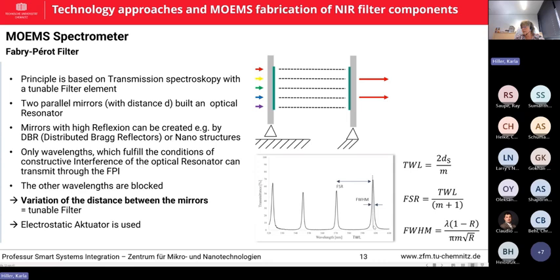And you can see here the transmission characteristics in a certain wavelength range. And this has some characteristic values like the maximum transmission. So 100% would be perfect. We end up maybe in the range of 60 to 70%. Then we want to have a narrow band filter. So this full width at half maximum should be as small as possible to have a good resolution. And we have also some limiting factors, for instance, this so-called free spectral range. So if the order goes higher, we get more peaks. That's a periodic signal, and we can work in one range defined by two neighboring peaks, which somehow restricts the working range of our filter.